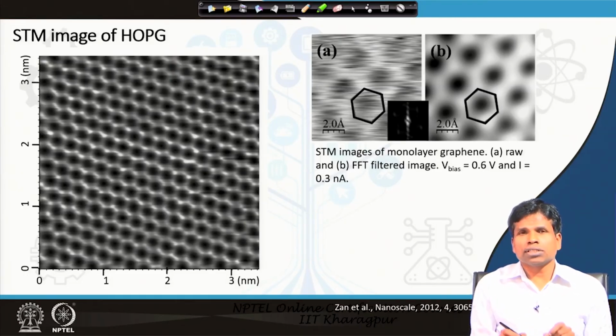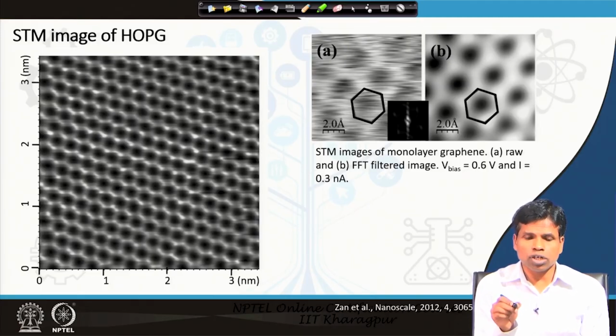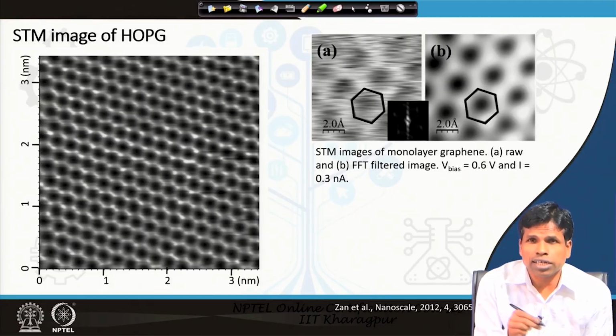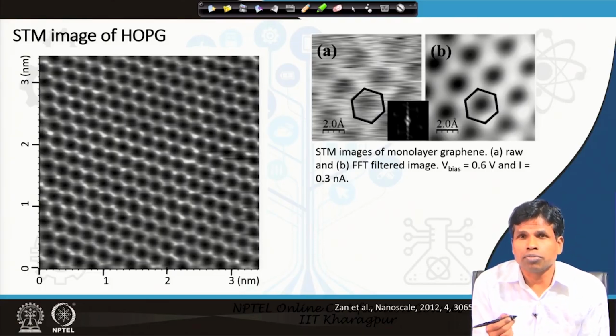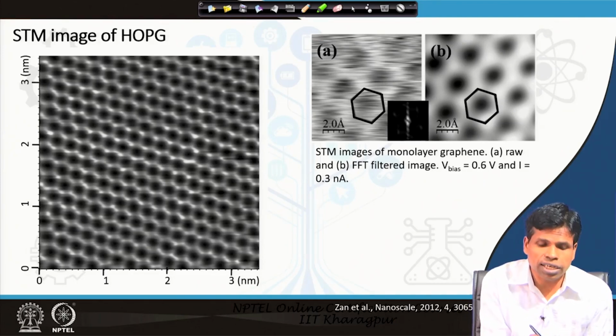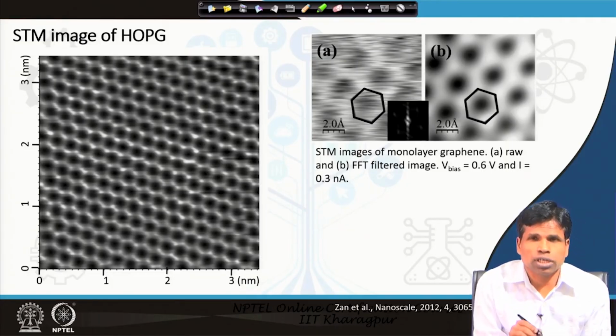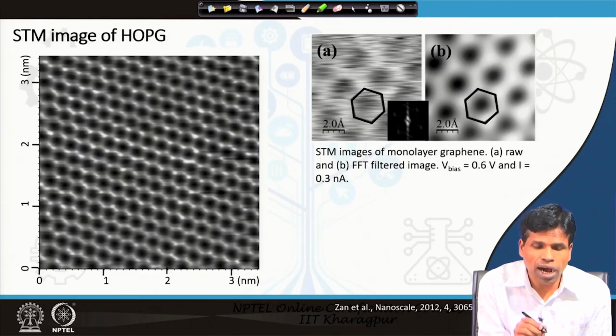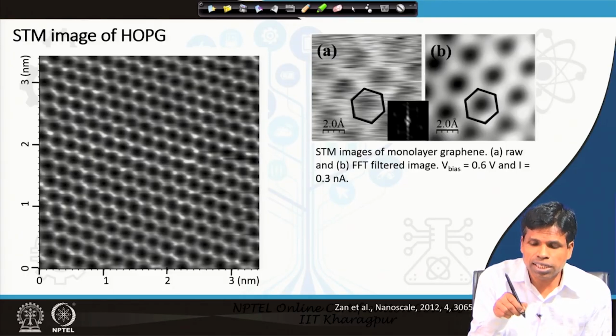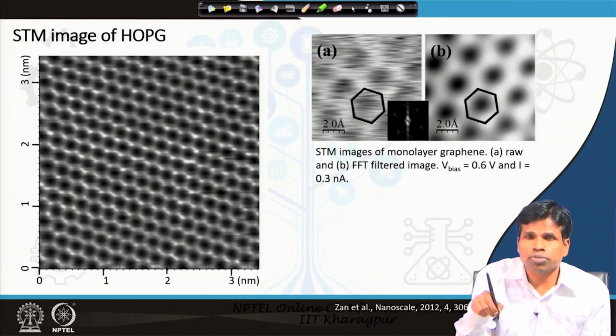At that place the tip measures current. So, therefore, you see brightness at the place where there are carbon atoms and there is bonding, and in the center of the hexagon you see dark, because there is no current available, because there is no atom available, there are no electronic clouds. Therefore, we do not measure any current at the center of a hexagon, therefore it is darker. In addition, if you look carefully, we could see that the contrast or brightness is a little higher at the corners of the hexagons where carbon atoms are present, because as it is a constant height mode, as the tip is moved across the sample,